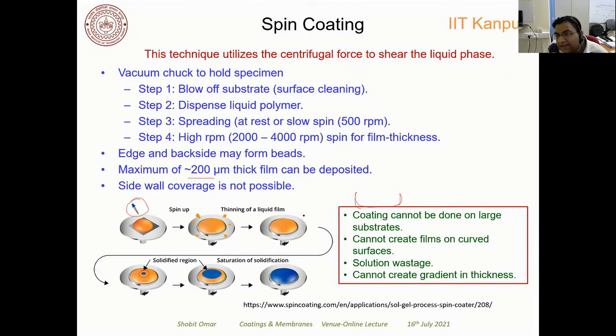So coating cannot be done on a very large substrate, because then you will require a large vacuum chuck to spin the substrate, and you cannot create film on a curved surface. And then of course there will be a lot of solution wastage, because this liquid will come out from the substrate, right? And of course you cannot create a gradient in thickness. Okay, that gradient cannot be made in the film thickness.